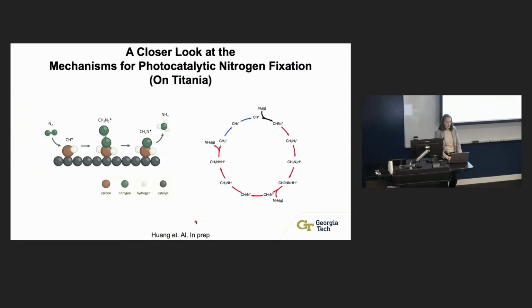They also have lots of different protons and electrons taking place in many different reactions in the enzyme. What we've been doing is looking at an alternative reaction pathway where you use those holes to oxidize a carbon species and create a high energy radical. That high energy radical can allow for the adsorption and activation of nitrogen. This is something you cannot do on an electrocatalyst, and you cannot do on a thermocatalyst. To me, that's the most unique aspect of photocatalysis.